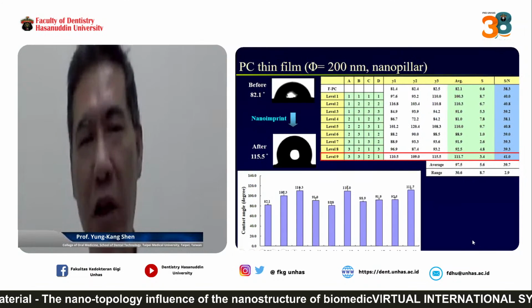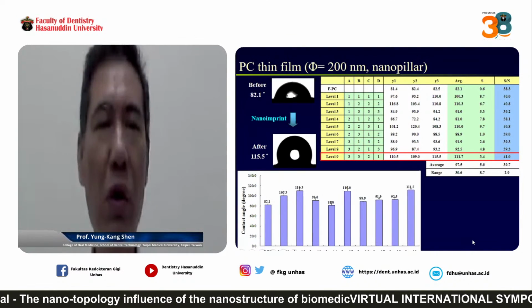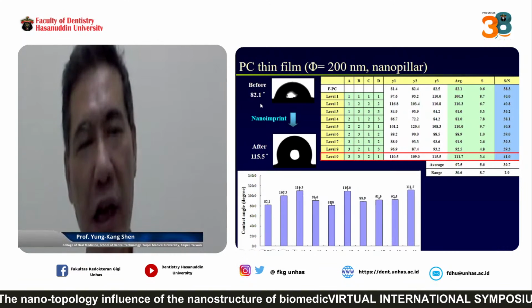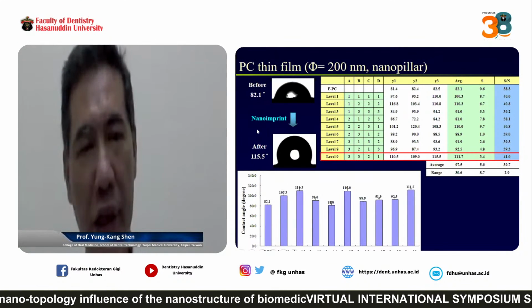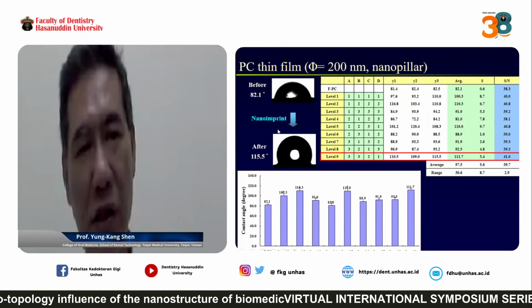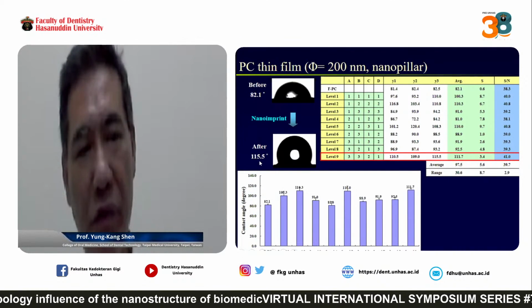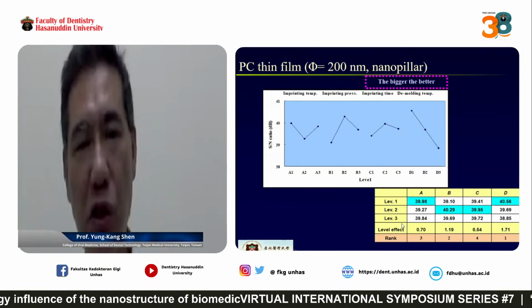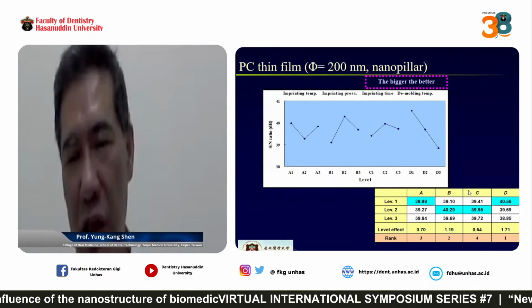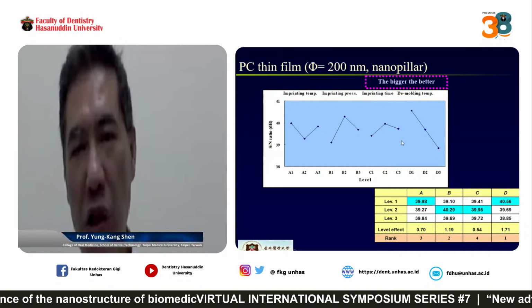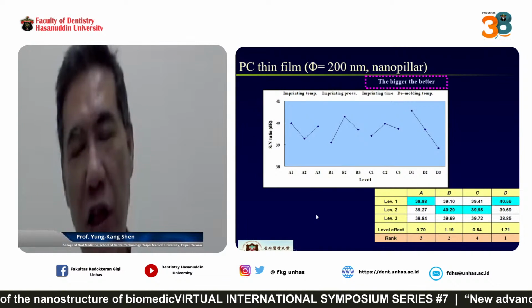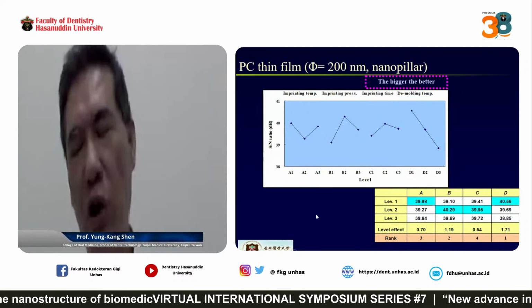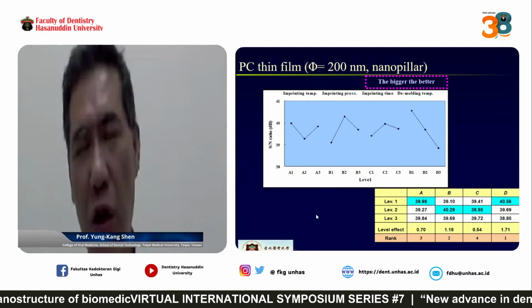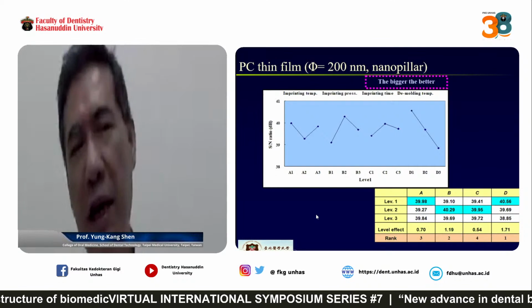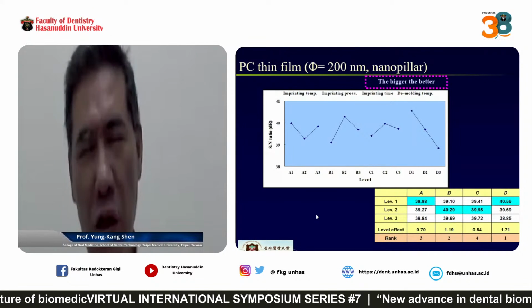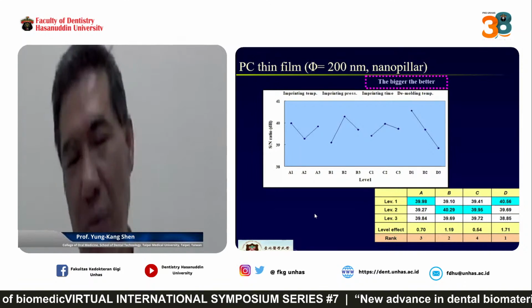So this is the PC thin film with a diameter of 200 nanometers. Before nano imprint, the PC thin film has a contact angle of 82.1 degrees. After nano imprint, making a nanostructure on its surface, the contact angle changes to 115.5 degrees. This is also the nano imprinting process. You can see here that demolding temperature is the most important factor. So we can make a simple conclusion: if you want to make a PC thin film with nanostructure, imprinting temperature is number one. If you make a PC thin film with nanostructure, demolding temperature is the number one factor.